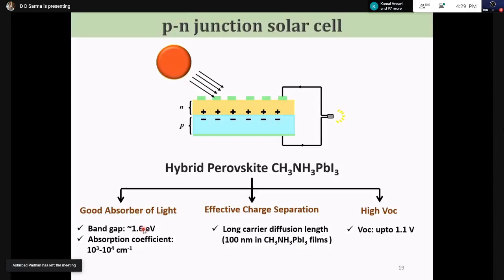Why do we have an ideal band gap? It's very easy to understand. Let me give you a quick one-minute detour explaining why you need an optimum band gap. If the band gap is large, the open circuit voltage is controlled by the band gap, because you cannot get a voltage that's larger than the band gap. So you increase the band gap, you increase the voltage. But as you increase the band gap, the photons coming from the sun which have energy smaller than the band gap will not be absorbed. So your current will go down.